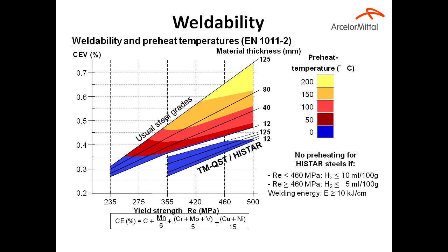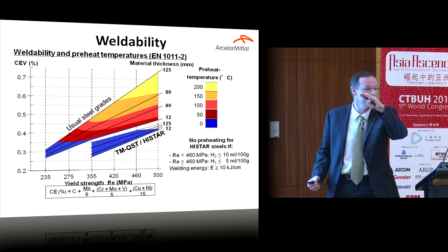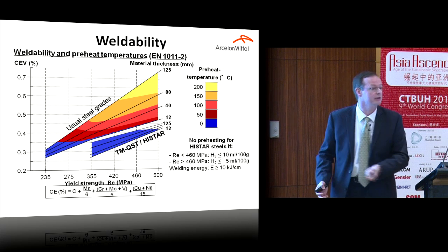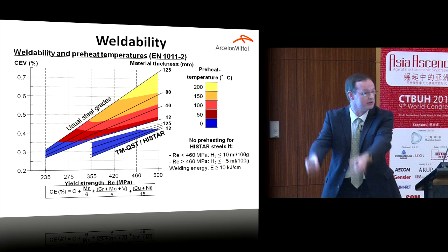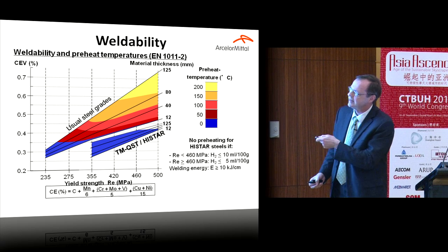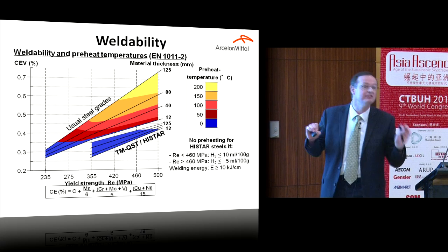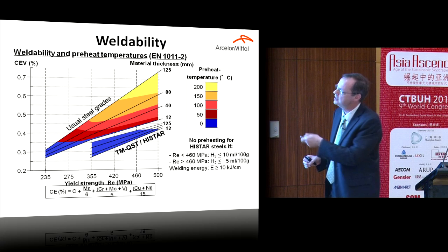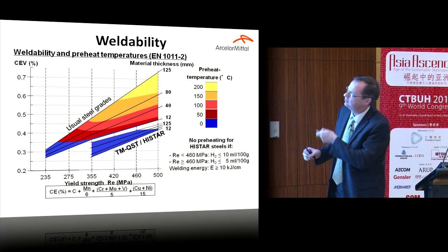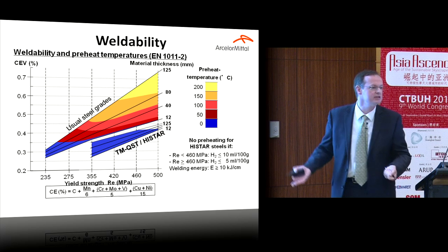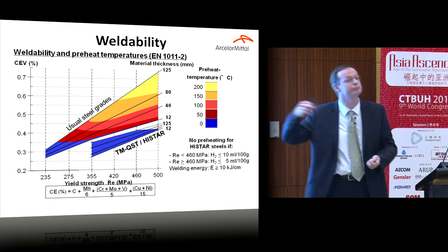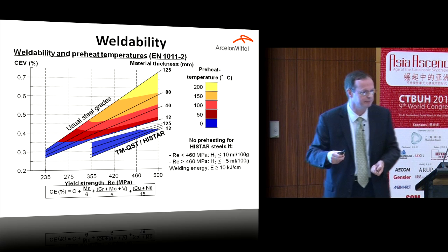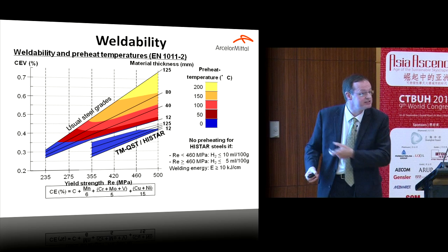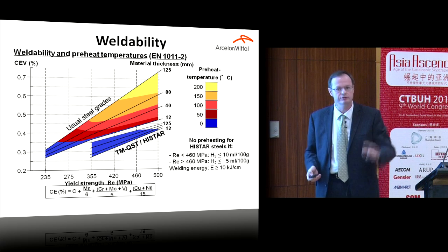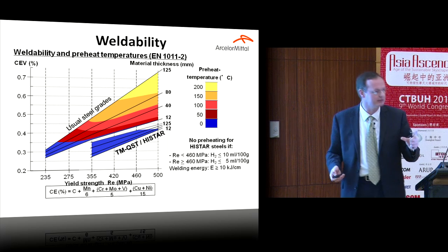When we have to increase the yield of the steel, we have to change the chemistry of the steel. We have to put more alloying elements into the steel. And if you use the classical way of making steel, what we call thermomechanical steel, for thick material you have to change the chemistry so much that the steel is not weldable anymore. This is why you have to preheat the steel before welding.